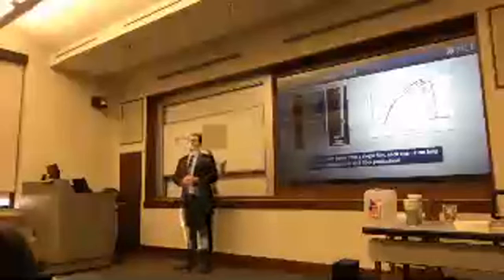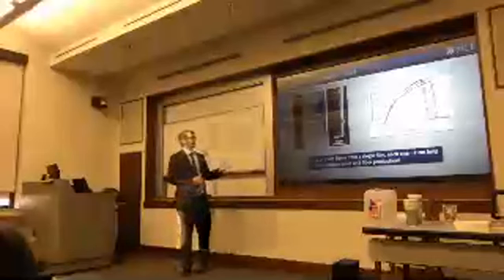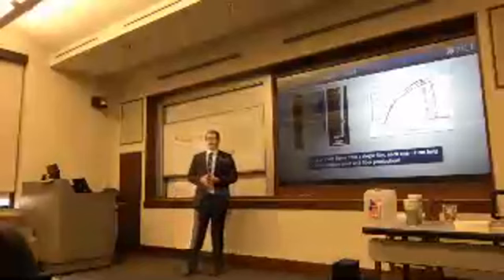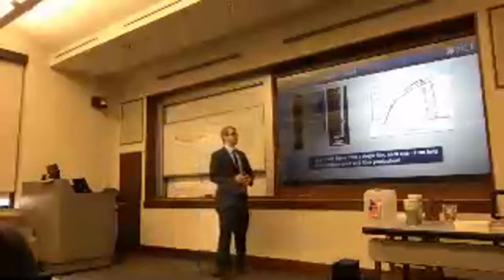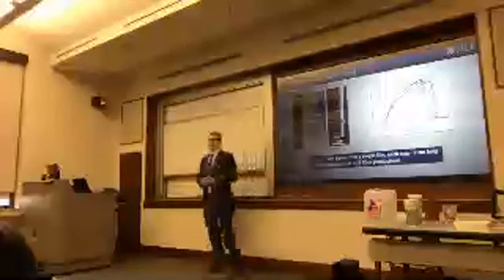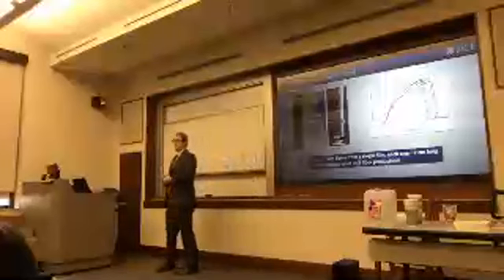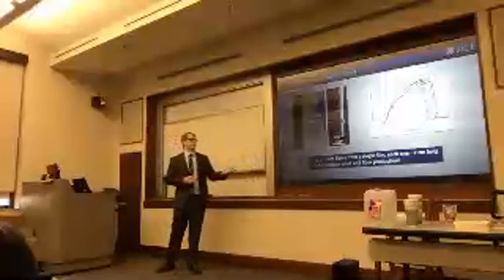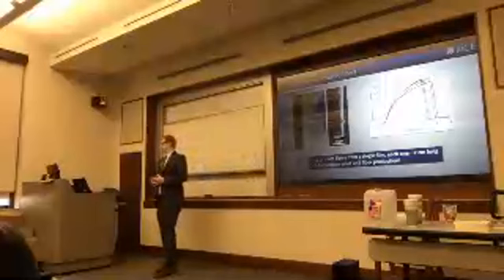One of those thin strips can be peeled and hand twisted into a nice cylindrical carbon nanotube fiber. And it turns out that these fibers have really high tensile strength. So here I'm plotting stress strain curves for 5 carbon nanotube fibers peeled from a single film, and you can see on average they have a tensile strength above 2.5 gigapascal.